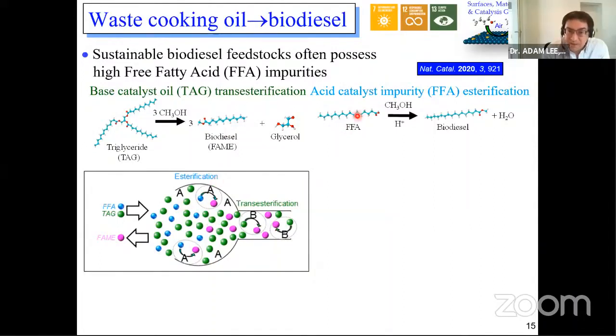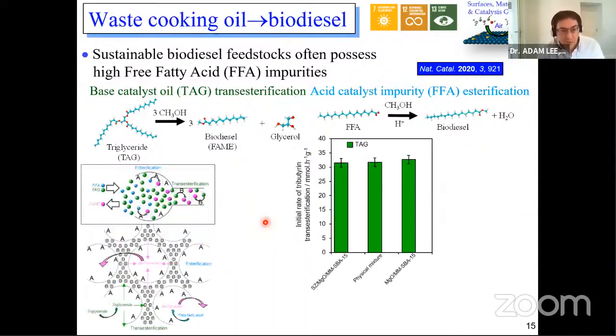We would remove the free fatty acid, and that would allow these green tag molecules to migrate all the way through into the smaller pores where they would find a base catalyst. And the crucial thing is that by removing the free fatty acids in this pore, we're protecting the base catalyst from ever being poisoned. That was the theory. So we made a framework, which you can see here, in which we would have esterification going on over acid catalysts in the large pores, and we would have transesterification, the triglyceride turning into biodiesel, over base catalysts in the mesopores.